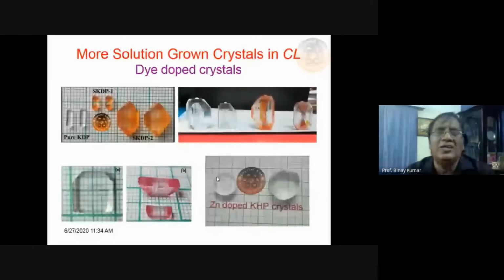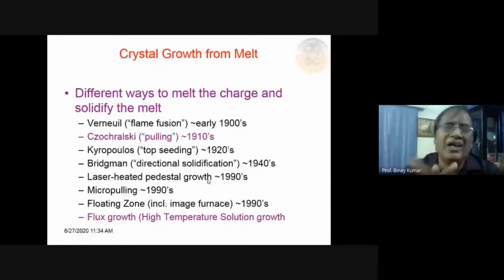Now come to crystal growth by melt. Melt means that we have a molten state of the material. For example, if we have some organic material, the melting point is 100 to 200 degrees Celsius. In the case of halide crystals, it is 700-800 degrees Celsius. Oxides are 1200 to 1500 degrees Celsius. Maybe silicon carbide, which is 2500 or 2700 degrees Celsius.